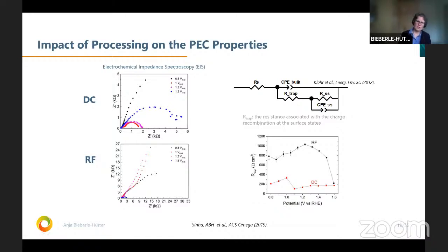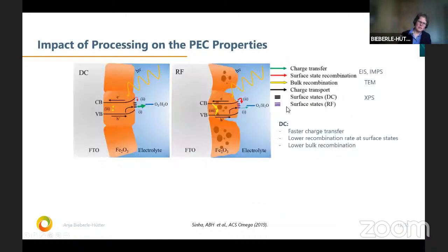So when we look at all these different elements, we can actually in the end then make these images about DC and RF. So what is now going on at these interfaces? And you see here that we add both the electrochemical data and what we have learned from the morphology and then the structural analysis. So we have holes for the RF in the thin film, and this makes that we get more bulk recombination here, whereas we have less bulk recombination for these DC films. Therefore, the arrows are smaller than these ones here.